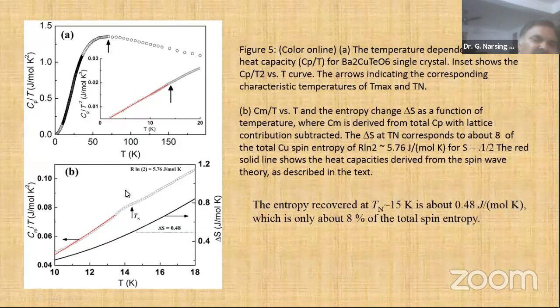This we calculated and considered many times. It means only 8% of the total spins are acting. That's why we don't get the complete peak or lambda type peak, because not all spins are acting at that particular temperature. If all were acting, the entropy should show 5.76, but the delta S we are getting at 15K is only 0.48. So only 8% of spins are acting in that transition.